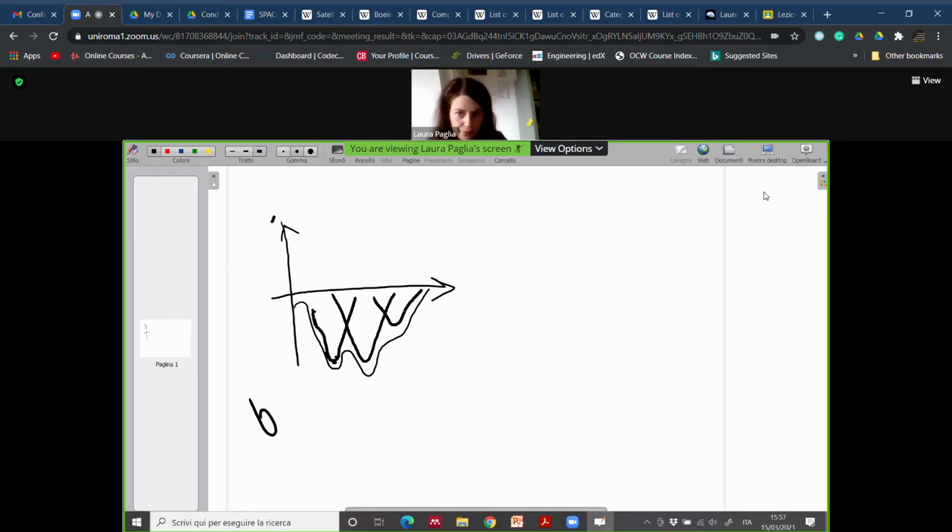I have to rebuild the derivative thermogravimetric curve with the sum of three different Gaussian curves, whose peak points correspond to the peaks in the DTG curve. Obviously this is very important.